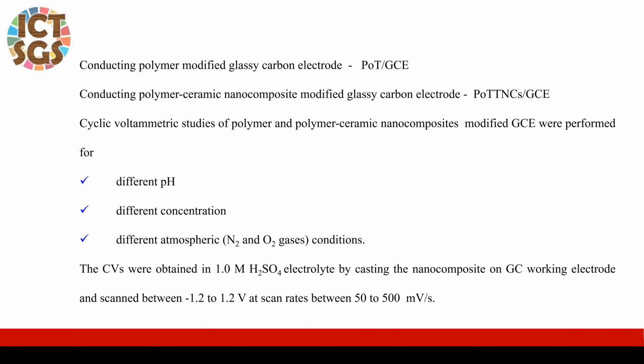Conducting polymer and conducting polymer ceramic nanocomposite modified glassy carbon electrode. Cyclic voltammetric studies of polymer and polymer ceramic nanocomposite modified GCE were performed for different pH concentrations and atmospheric conditions. The CVs were recorded in 1 molar sulfuric acid electrolyte by casting the nanocomposite on the GC working electrode and scanned between -1.2 to 1.2 volt at scan rates between 50 to 500 millivolt per second.